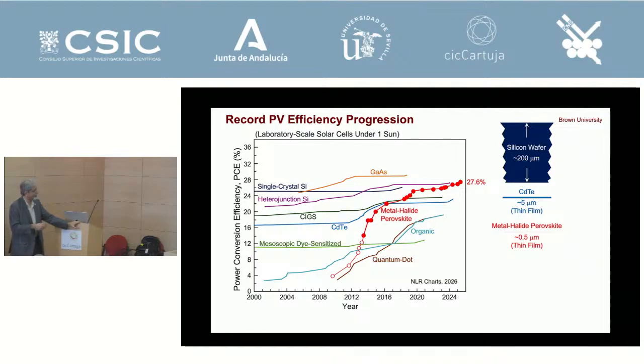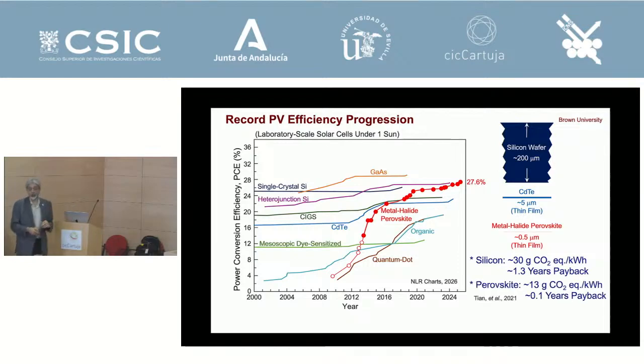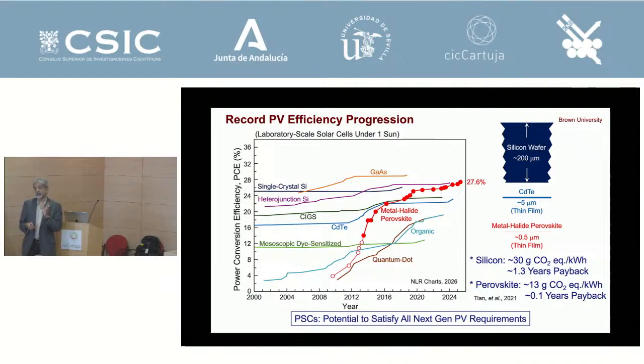And so this is where perovskite came in. And you can see why there's this excitement in this field, is that it went from about 4% to today 27.6% efficiency, which is about the same as silicon, right? And you can see that this is a thin film material. A silicon wafer is about 200 microns. This is half a micron. 500 nanometers is all you need for all the absorption of the solar spectrum, and you can produce electricity, right? And also, if you look at the payback time and carbon footprint, it is much lower than silicon, right? And so this perovskite basically has the potential to satisfy all the requirements for this new type of solar energy for pennies per watt in potential, right?